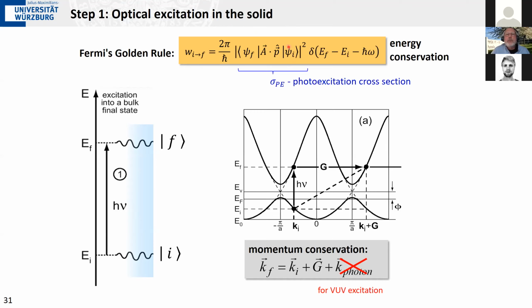where you go from the initial state to the final state via this transition operator, and that's basically the vector potential multiplied with the momentum operator, A dot P. This is basically at the end the conventional dipole approximation. And you have energy conservation here. You have this delta function, which ensures that if you start with the initial state energy of electrons and you add the photon energy, you end up at the final state energy at which the photoelectrons get detected.